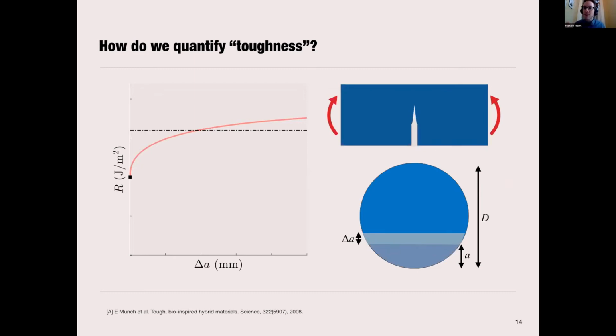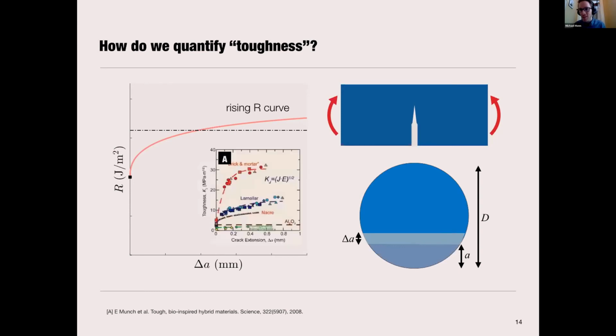We're not trying to necessarily discover the mechanism here, that'll come a bit later, but really capture the effects of the mechanism on the energy dissipation in the system. This increase in R can be due to a number of extrinsic or intrinsic factors that occur both behind or in front of the crack tip. So rather than trying to measure the entire R curve, which can be complicated with materials that have extrinsic toughening mechanisms, we're going to characterize it by two specific points. That is R at 0, which is the fracture initiation toughness by another name, and the average value.